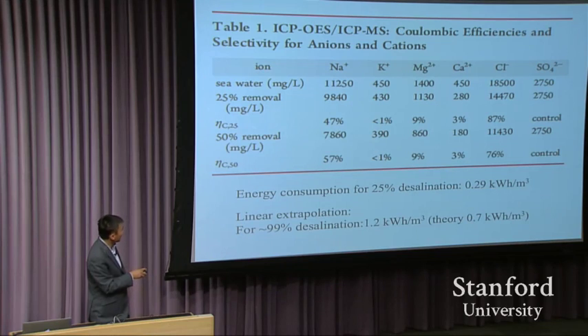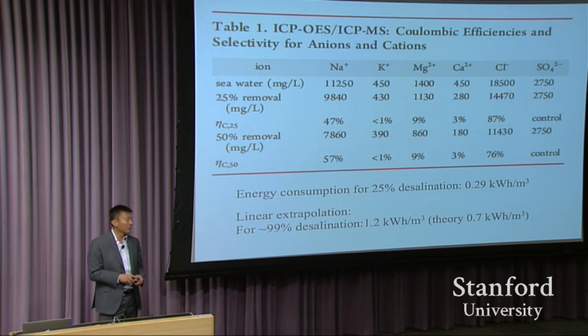For 25% desalination, we calculate that we consume electricity of about 0.3 kilowatt hour per cubic meter. If we do a 99%, I only assume linear extrapolation, of course, and in the real technology, this won't be linear. We're going to consume more energy than this linear extrapolation. If we do a 99% salt removal, we will consume 1.2 kilowatt hour per cubic meter. We are doing pretty good. Theoretical is 0.7 kilowatt hour per cubic meter. So we are somewhere close to about double. This is much better than a reverse osmosis process.